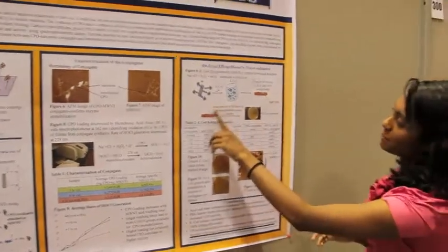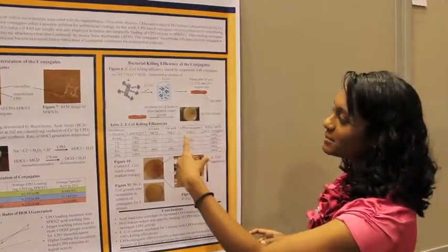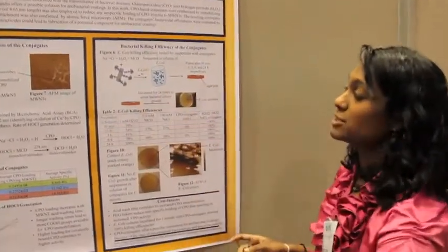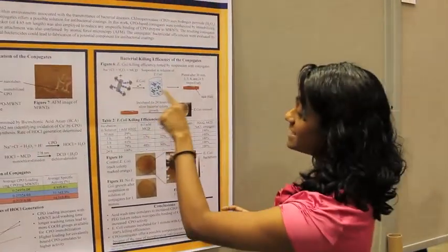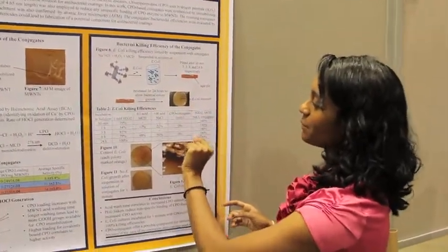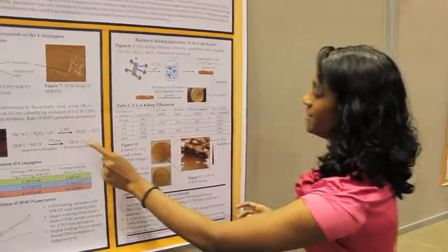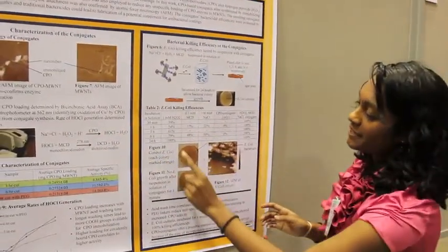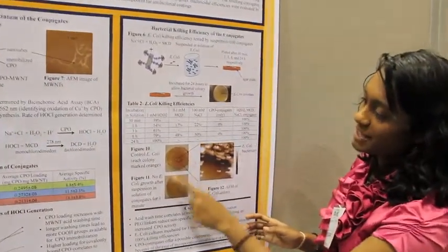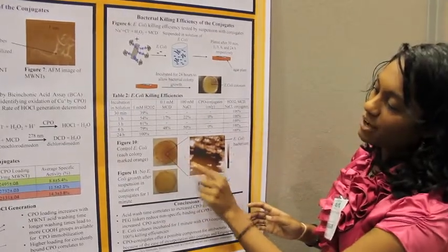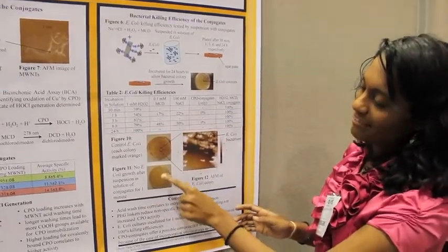And the next step was to see what their bacterial killing efficiency was by suspending them in solutions of E. coli and seeing what happens. And we found that whenever you combine all these components, within 1 minute, the killing efficiency is 100%. So this one is the control. Each of the colonies are marked orange, and then this is after a minute.